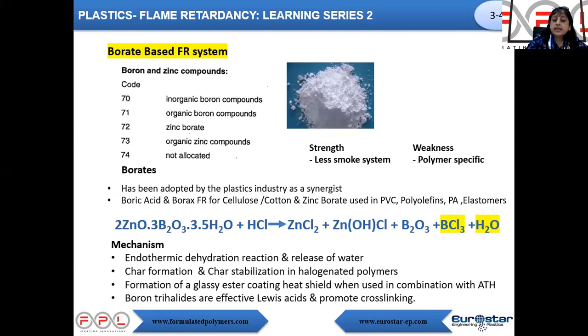So boric acid and borax have been used in the cellulose and cotton industry for a very long time. Zinc borate has been used in vinyl chlorides, olefins, and polyamides. Here also, what we see is an endothermic dehydration reaction with the release of water. So water is released, and char formation and char stabilization is due to the halogenated part of the system. The formation of a glassy ester coating, which acts as a heat shield when combined with ATH, is what gives it the synergistic effect.